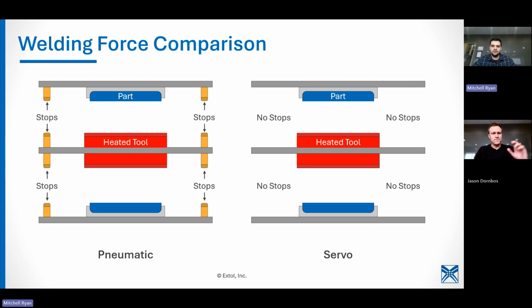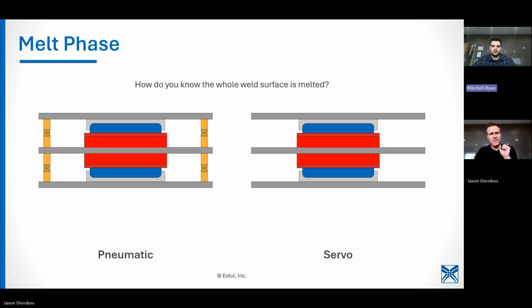That's important. So when we come together for the melt phase with a pneumatic welder, how do you know that the whole weld surface is being melted? You can adjust the positions of your hard stops, but there's not really good feedback to know you've melted your entire surface. In a servo-driven welder, you can dial in the amount of melt that you're applying to the part, making sure that 100% of that weld surface is making contact.